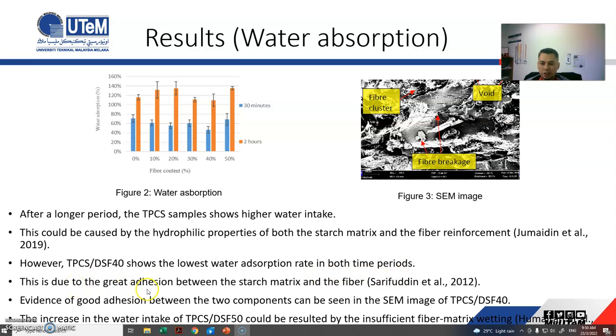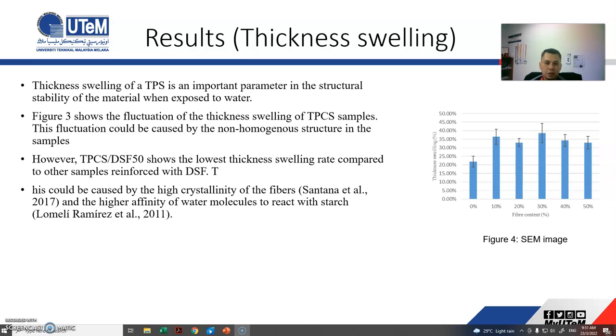This can be due to the great adhesion between the starch matrix and the fiber. Evidence of good adhesion between the two components can be seen in the SEM image here. As you can see, this is the fiber, this is the matrix. The fiber is well bonded with the matrix, so this is the evidence of good adhesion. The increase in water intake for the 50% sample can result from insufficient fiber matrix wetting, because when there are too many fibers in the composites, the wetting becomes weak and thus affects the water absorption of the materials.